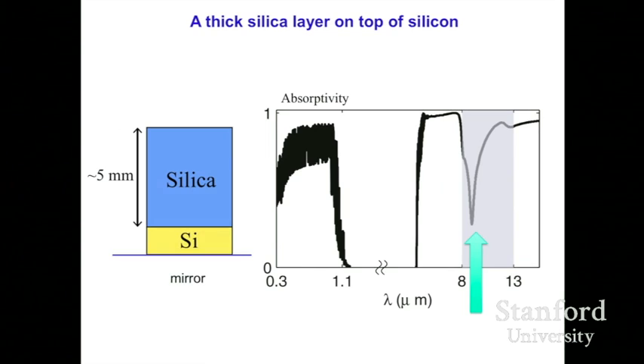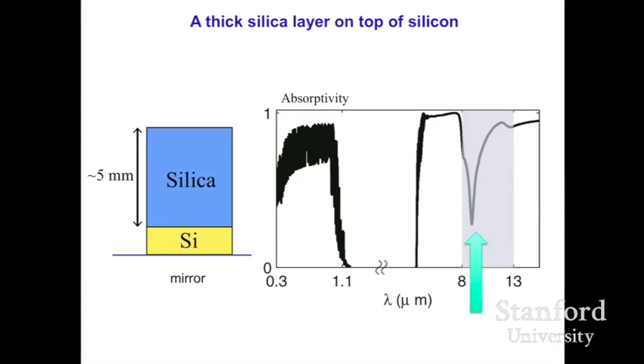So one material that one can use is silica. As I mentioned, silica has a strong thermal radiation and also is transparent. And so you can imagine putting a thick layer of silica on silicon. As you do that, it doesn't affect the absorptivity of the silicon region much. It does enhance the emissivity in the 8 to 13 micron window.